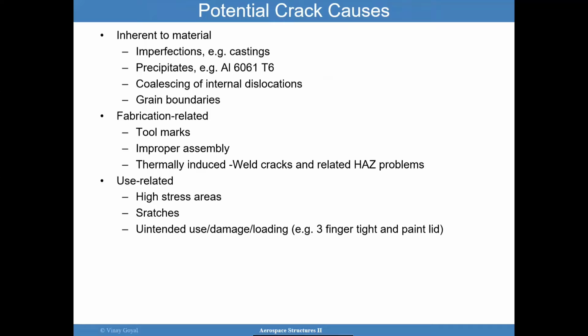So potential crack causes could be inherent to the material, such as imperfections in castings, precipitates in aluminum 6061 as an example, coalescing of internal dislocations, or you may have grain boundary issues. You could have fabrication-related issues, such as tooling marks, improper assembly, thermally induced cracks, such as areas that have been affected by the heat. You have use-related issues like high-stress areas. You can have scratches or unintended use being a problem.